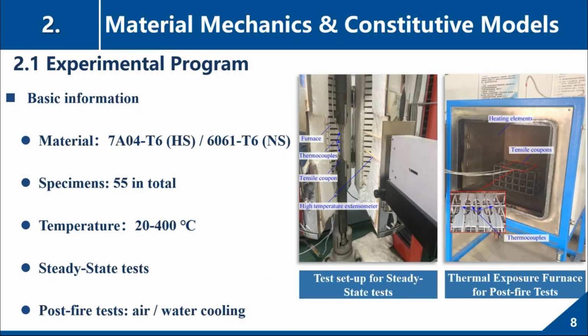Specimens were tested in the range of ambient to 400 centigrade, and these tests were carried out in two conditions. The first one is steady state. The second one is the post-fire state. And for the post-fire cases, there are two kinds of cooling method, air and water.